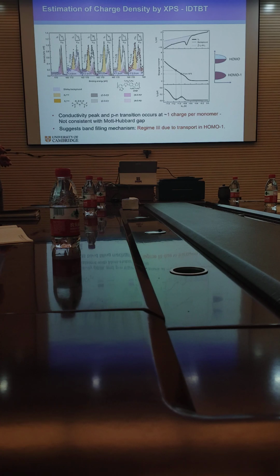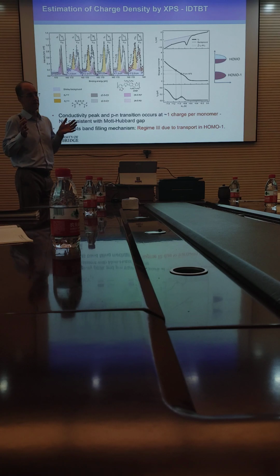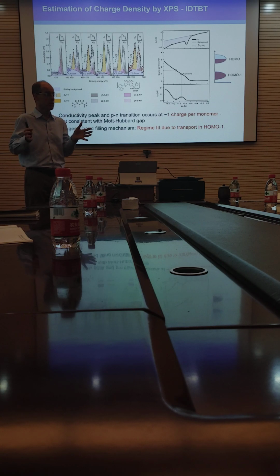It doesn't make sense. So in order to understand what this is, you have to, of course, ask yourself, what's the actual carrier density? So we went back to our XPS technique and determined, at the different operating points along this transfer characteristic, which I've reproduced here, what the carrier density is. What we found is that at the first peak in the conductivity, the carrier density from XPS is exactly 1 charge per repeat unit. What that means is that the HOMO band is half filled at that point. The HOMO band has 2 electrons per repeat unit, so if you have 1 charge per repeat unit, the HOMO band is exactly half filled.